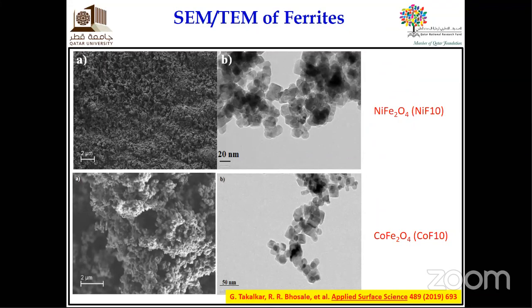These are the sample images. Actually, all the images look like this. So I just put the sample images for selected nickel ferrite and cobalt ferrite materials. The SEM images are on the left-hand side, and the TEM images on the right-hand side. So if you check the bar, which is 20 nanometer in the first picture and 50 nanometer in the second picture, you can clearly see that we successfully synthesized the nanoparticles of nickel ferrite and cobalt ferrite. So after doing this, the material is done now. We synthesized nickel ferrite, cobalt ferrite as we wanted. Now the next step is to test them.